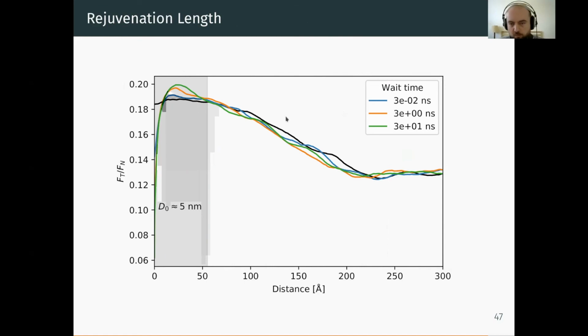And you can see in black, you have the steady state curve, which has no interruption in the sliding process. In blue is a rather low waiting time, and then you increase the waiting time. So you have this increase in the overshoot of the friction force. And this overshoot is a transient that decays and reaches the steady state again after a sliding distance that's about 5 nanometers. So those are like 51, 52 angstroms. So this is something very encouraging that corresponds to the experimental measurements.